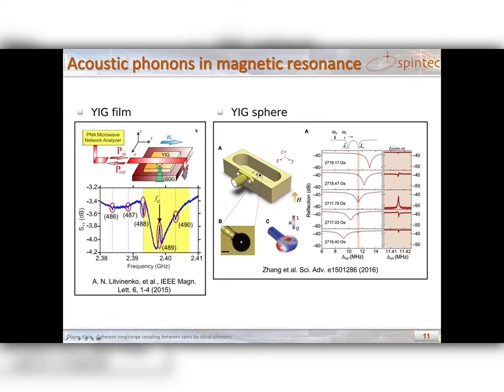So as I've said before, the manifestation of acoustic phonon has already been observed in several FMR experiments. I would like to concentrate first on this experiment done on YIG thin film, where one can see that the broad ferromagnetic resonance peak is actually decorated by tiny sharp peaks, which are regularly positioned in the frequency domain. They are periodic in the frequency domain. And sometimes these peaks become dips, or they have a dispersion-shape-like form. And this periodic feature should be associated to acoustic resonance across the whole crystal thickness.